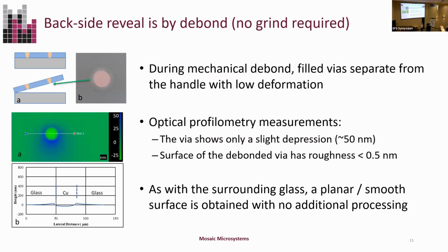What this means also is that, again, in a TSV, typically you would do a grinding process to reveal the backside of your via. In this case, we would do our post CMP anneals in situ on the handle. And then when we debond, the reveal is just the back of the glass is there. So we've done optical profilometry measurements to show that basically it's a very coplanar surface there within 50 nanometers. I'm going to try to get my factors of 1,000 right there. So it's a very simple backside reveal.